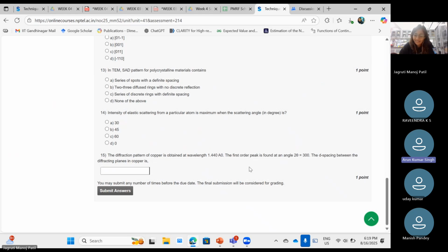In last week's assignment also, the formula told by the teacher was different from whatever formula is used in the question, and that's why it is wrong. You have also shown that beta opt is 0.67 lambda to the power 1 by 4, Cs to the power minus 1 by 4. But in the question solving, it is only beta equal to lambda to the power 1 by 4 divided by Cs to the power 1 by 4. There is no constant in the answer. Perhaps they have not mentioned the constant there, so they assume there's no spherical aberration effect happening.